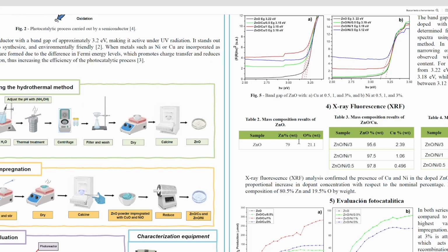I'll continue with the fourth characterization, which is X-ray fluorescence to determine the chemical composition. In the first sample, we found that it was exactly 79% zinc and 21% oxygen. Subsequently, it was impregnated with 3, 1, and 0.5%, where we can see that for 3% it was 2.39, for 1%, 1.06, and for 0.5, 0.49. So we have a very acceptable mass percentage of the metal in the zinc oxide.